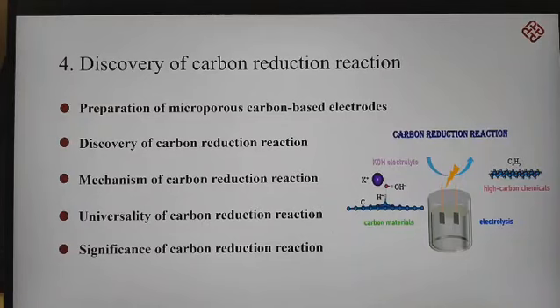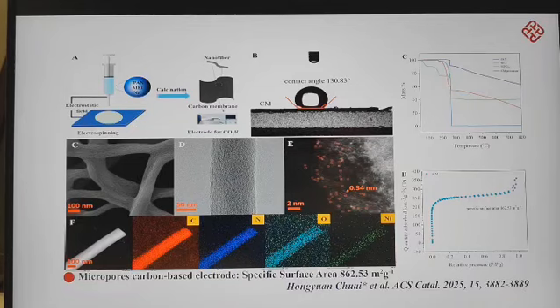To further optimize the performance of carbon-based electrodes, we added melamine as a pore-forming agent to the precursor to prepare carbon-based electrodes with microporous structure, and in this work, we discovered a novel carbon reduction reaction. As shown in the figure, melamine completely decomposed during pre-oxidation, resulting in a surface covered with micropores on the carbon fibers, with a specific surface area as high as 862 square meters per gram.